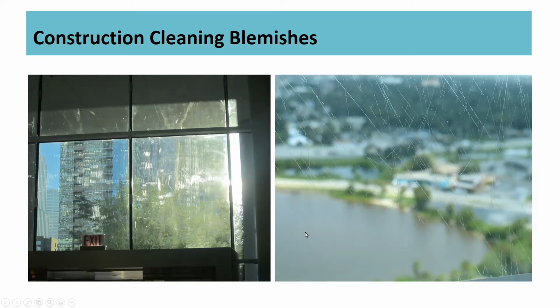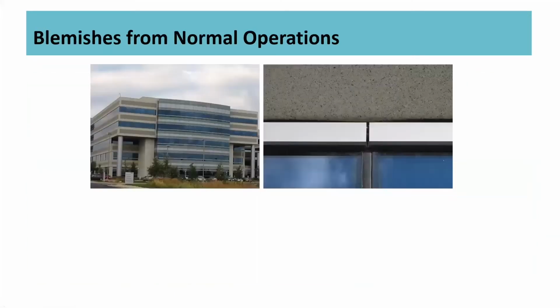But it can become very extensive. As you can see in the right-hand photo, under sort of nondescript, cloudy day conditions, the glass scratches are very prominent. In the case on the left, we almost left the project without identifying any egregious surface blemishes until fortuitously the sun came down on the horizon and illuminated these, what we would term angel hair scratches on the glass, and they were widespread and over the majority of the glass surface. So you can see that lighting conditions have a significant role in the identification of scratches and blemishes as well.